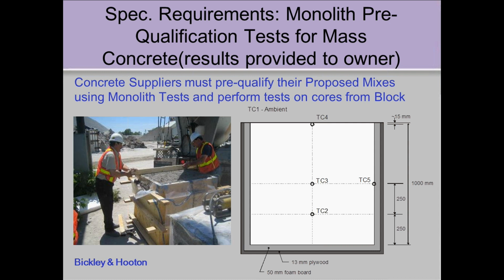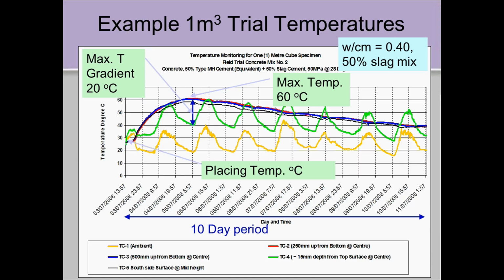Some of these elements have actually used bigger sections, some of them 2-meter sections. So they've adapted this concept of using a monolith pour in their specs. This is one where we did one trial mix with a supplier, and it shows the temperature variations during the day at the surface and just near the surface. And there are the internal temperatures, which go up to 60, and their gradients were about 20 degrees in this particular concrete mixture that they're evaluating.